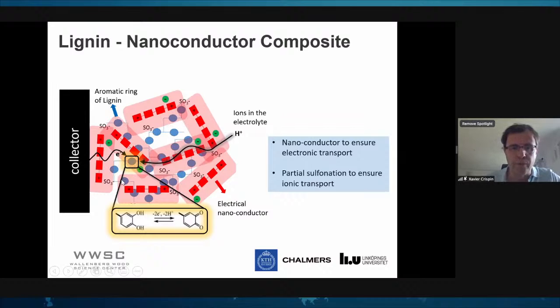Lignin is depicted as the network of blue things here, and each of those bonds is actually a quinone and hydroquinone group that can store 2 electrons, and needs to exchange with the electrolyte, in that case protons. Since it's an insulator, you would need to bring a nanoconductor so that electricity can be brought to each site, and they must be very small. I depict these nanoconductors as the red solids here. The red solids are going to conduct electricity, so the electron can come from the electrode and reach those sites. From the electrolyte, a proton can also travel through the material and reach the same site. If that occurs, then you can have this redox reaction in the quinone, and you have the ability to store 2 electrons per ring, which is quite a decent energy storage material.